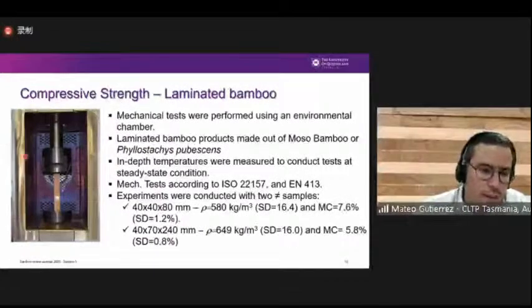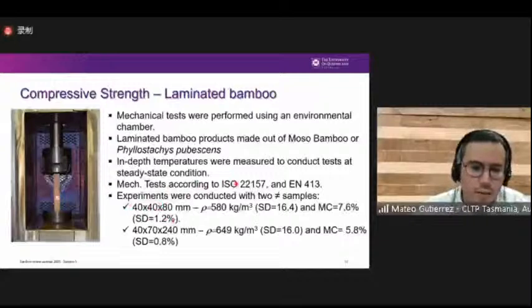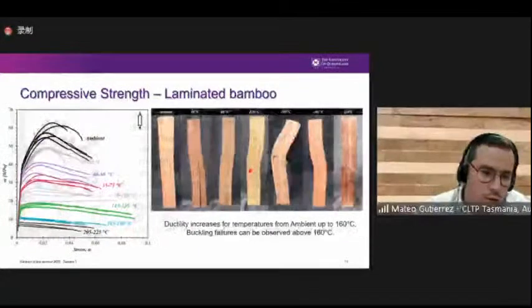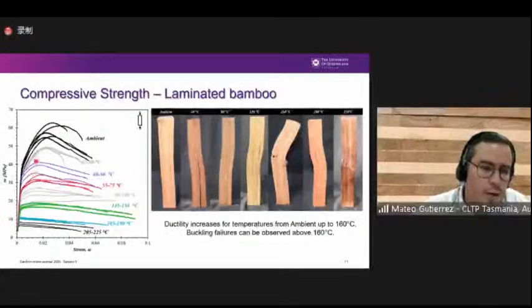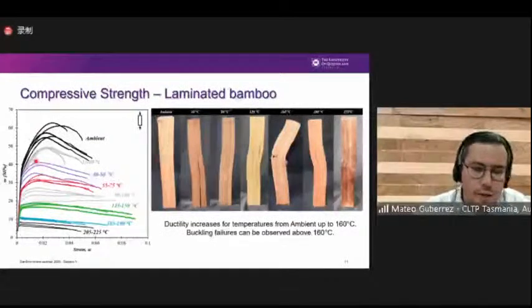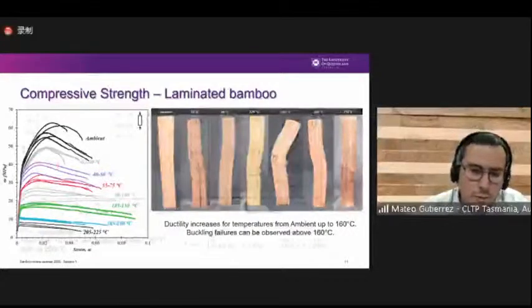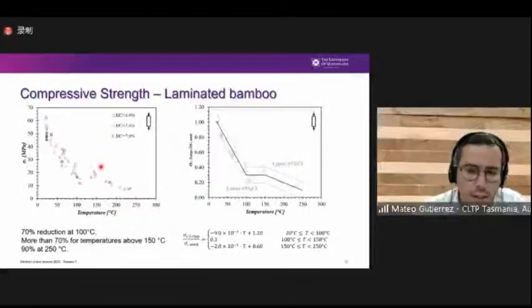So we basically repeated the same testing conditions. We tried two different materials. We followed not only the bamboo standard, but the European standard on laminated timber products. And then we observed the reduction in the compressive strength. We looked at the variation in the stress strain curves, and we also observed changes in the failure mechanism of bamboo. We obtained the reduction factors at elevated temperature, and then we studied some equations to predict the performance of the material.